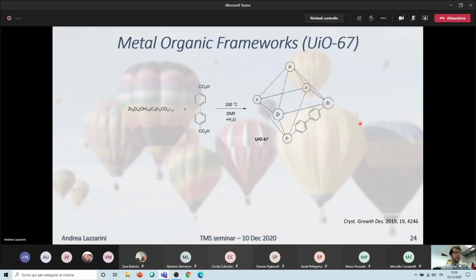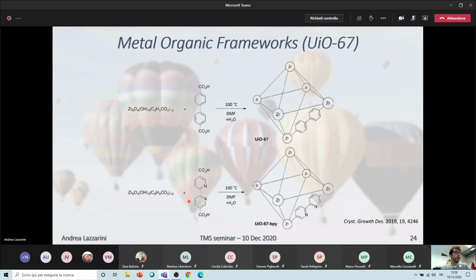But in our case, we developed a structure where bipyridine rings can be isosubstituted, since they have the same steric hindrance in the structure. You can change up to 10% of the linkers with bipyridine rings, and the two nitrogen atoms can provide the anchoring point to graft a metal ion in order to perform catalysis. In our case, we were loading palladium and platinum mostly.